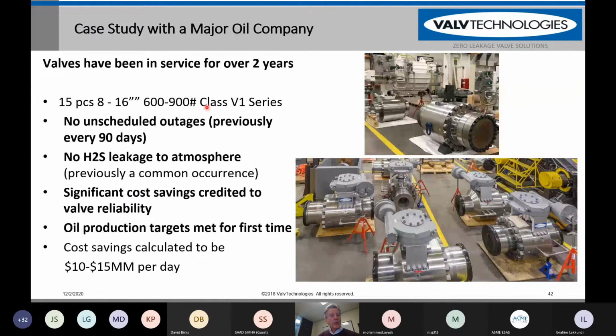So this major oil company came to us after talking to many other end users around the world, and they ordered 15 pieces of 8-inch through 16-inch, 600-pound class through 900-pound class valves. Here's some of those valves right here in our factory. These were made of solid Inconel with Inconel 718 trim on the inside because they had very severe H2S service. They had 17 to 21, 22% H2S and a lot of sand going through the valves. Downstream of the separator, the gas was passing through these valves, so they put our valves in service.